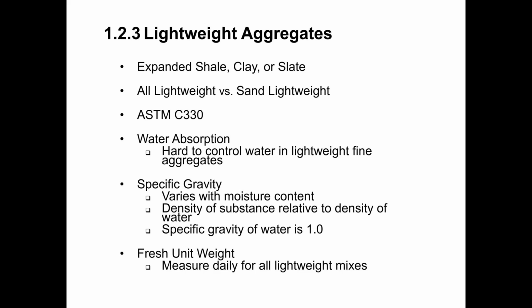Also, the test method that's required is different. Most plants will use a pressure meter to evaluate air content in a mix, but if it's a lightweight mix, we can't use the pressure meter. We have to use the Roll-A-Meter, which is a little bit more involved, usually takes a little bit longer. It's a little bit more complicated test to perform. All right, so our quality control, we're going to do testing more frequently, and the test method that we're going to use is a little more complicated than the test method that maybe we would use with a normal weight aggregate. So those are some things just to keep in mind when you are dealing with a lightweight concrete mix design at a plant.